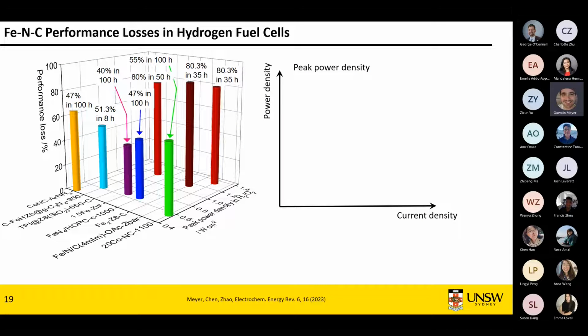So again, as I was saying, on this graph over there, you can see the performance loss over time. I spent far too much time during lockdown making this figure. But what you can see here, these are the record-breaking catalysts. And basically in 35 hours, there is only 20% of the performance left. And this happens for all sorts of catalysts in literature, and they all lose stability extremely quickly. This one lost 50% in less than 8 hours. So that's even scarier.